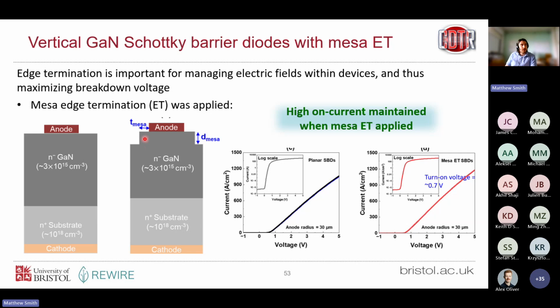And we played around with some of these parameters. So the spacing between the edge of the MESA and our anode contact, and also the depth of the MESA as well. So again, good news in the on-state, changing things around up here didn't really have an effect on our on current. Looks fairly similar between the two devices. Slight drop when we apply the MESA edge termination because we've reduced the current density slightly, but that's fairly negligible. Both these devices have a quite low turn-on voltage, reasonably consistent with what we expect from the work function and the